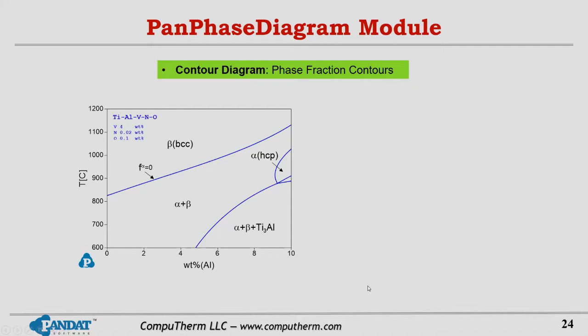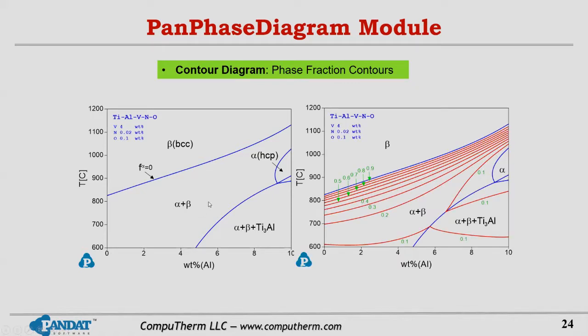This titanium alloy is in the alpha-beta region, for example. However, this alpha-beta region is a large region that varies with composition and temperature. It's not obvious how much alpha and beta you can get for a given composition and temperature. However, if we plot phase fraction contours on this diagram, then we can immediately see what's the fraction of alpha and beta at each composition and temperature.